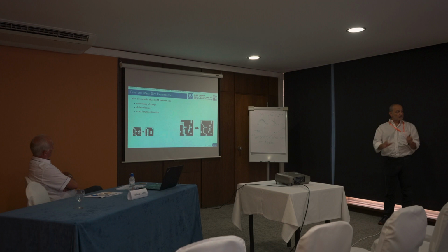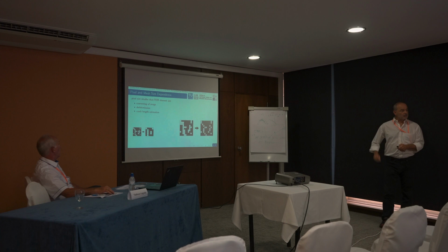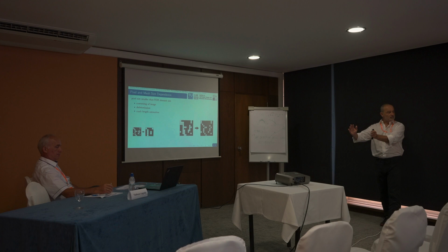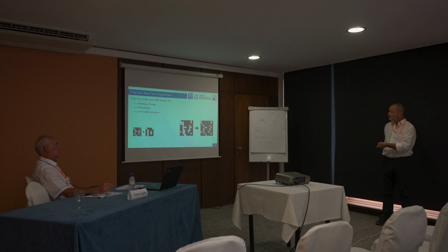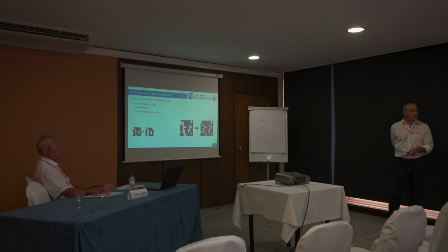Typically, the pixel size of the images is much smaller than our finite elements, so we have to make this match somehow. And first, we have to coarsen the information from the image, so to blow up the pixels, more or less, which is shown here. So we just go from the pixel size of the image, make it comparable to our finite elements. Then we have to do skeletonization, which means we do not want to have 3 or 2 pixels in a row. We just take out one of these, so that we have really a sequence of pixels, and at the end we do a length estimation. So if the crack runs perpendicular, it's shorter, than if it runs diagonal, it's a little bit longer. So this is also taken into account to have a more realistic measure of the crack length.